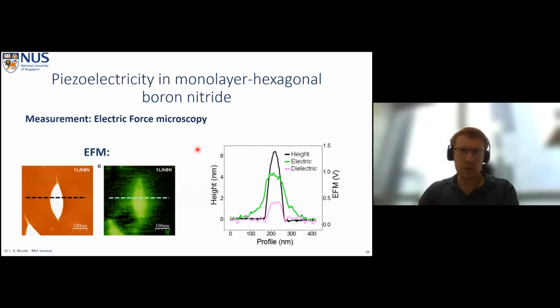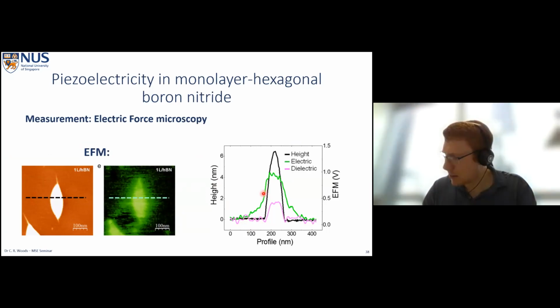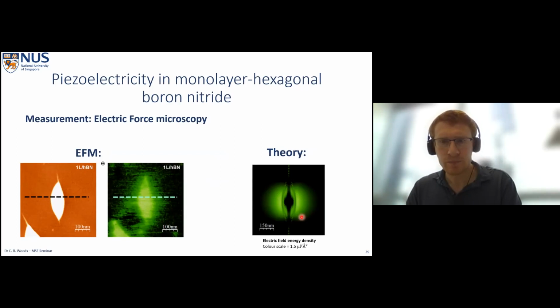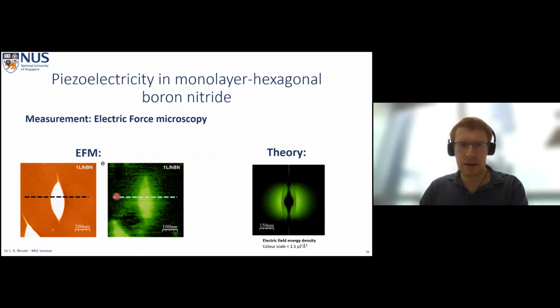We look at several different bubble types, and we always see the same behavior, where the second harmonic, the dielectric signal, drops to 0 as soon as we leave the bubble's immediate vicinity. But the electric signal, the first harmonic, propagates hundreds of nanometers into our stack, as expected from our theory. There's the theory for a bubble of this kind of shape.